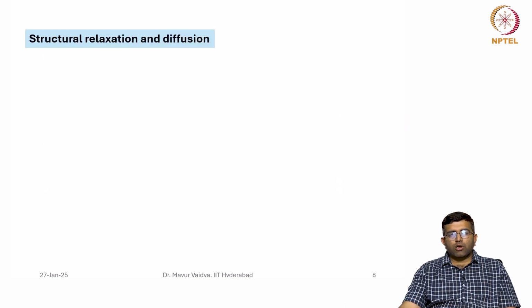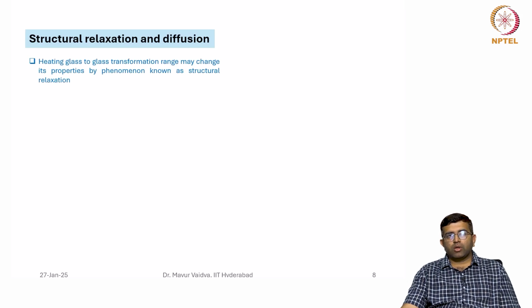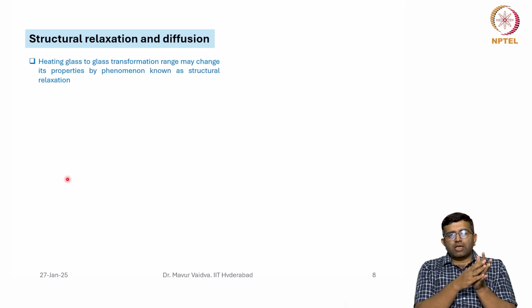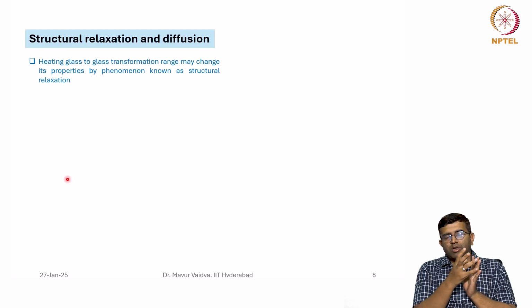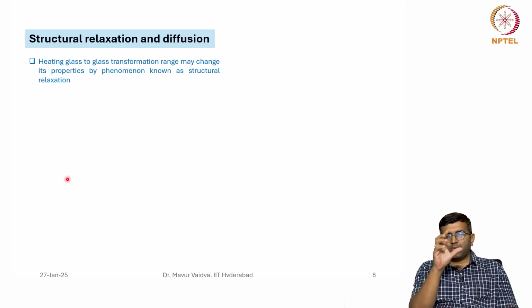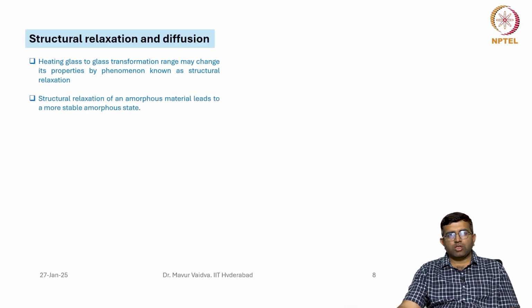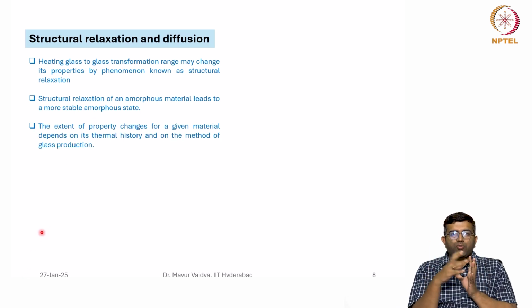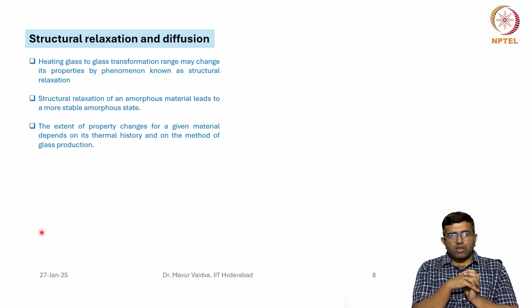Now, let us talk about what is known as structural relaxation and its impact on diffusion. If you heat a glass to the glass transformation range, then it may change its properties by a phenomenon which is known as structural relaxation. That means we are heating it below the crystallization temperature, but above the glass transition temperature. When structural relaxation happens, it leads to a more stable amorphous state. How much the properties change depends upon the given material, its thermal history, and the method of glass production.